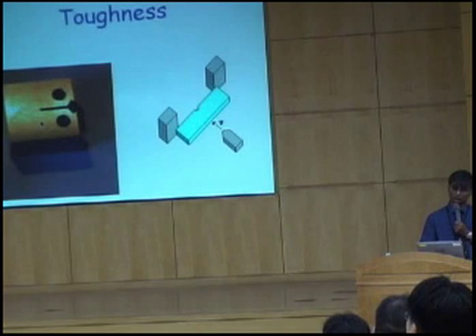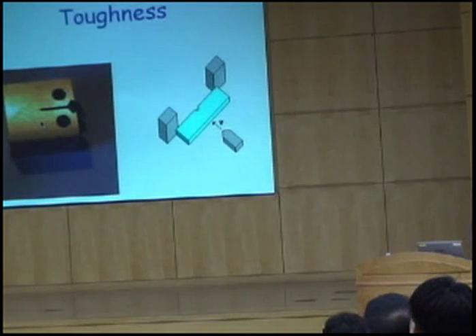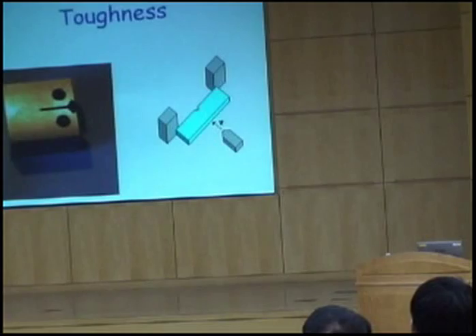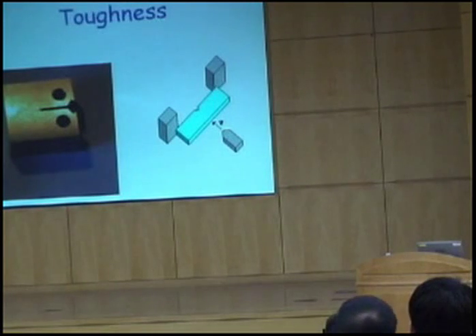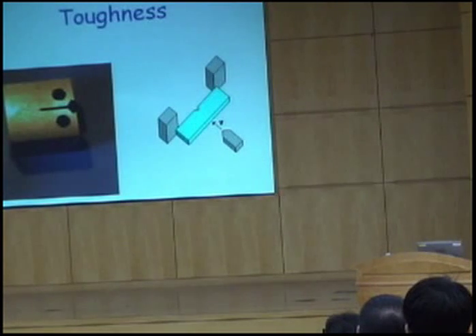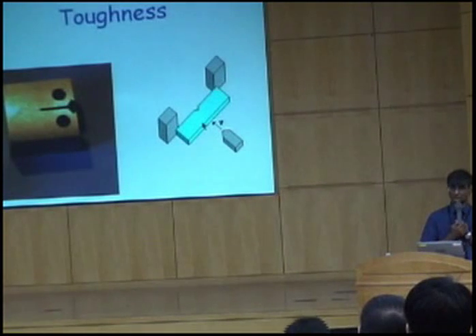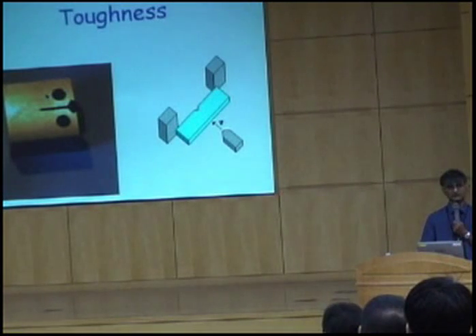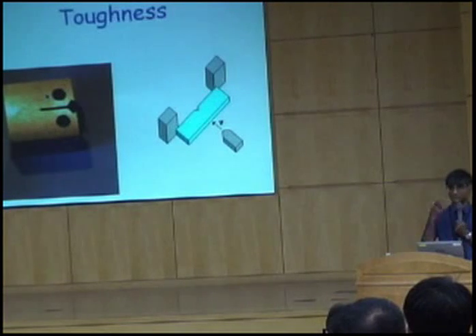This is a more fundamental material property. It's a K1C, or fracture toughness test. The number that you get from a K1C test, you can actually use to design a structure and say that this structure will be safe if the crack or defect is less than a certain size. It will not fracture by rapid fracture. So there are many different kinds of tests, and all of them are important. This one tells you immediately if something has gone wrong in your steel production. This one gives you a number which you can use to design a ship or an offshore structure or whatever.